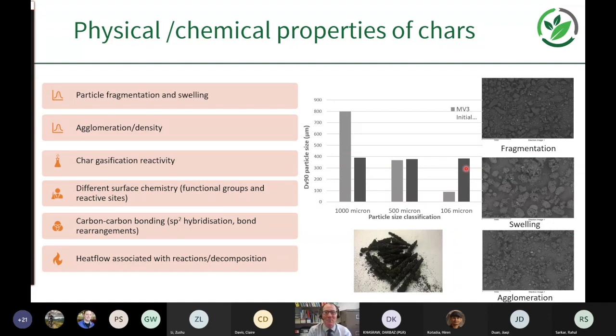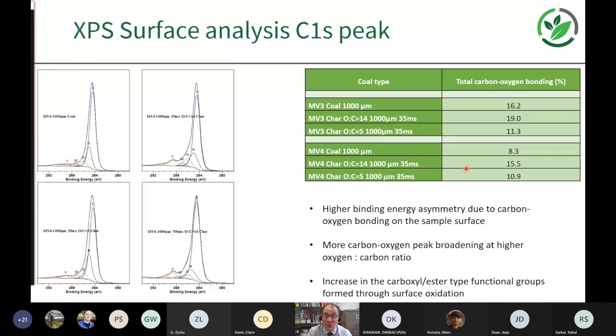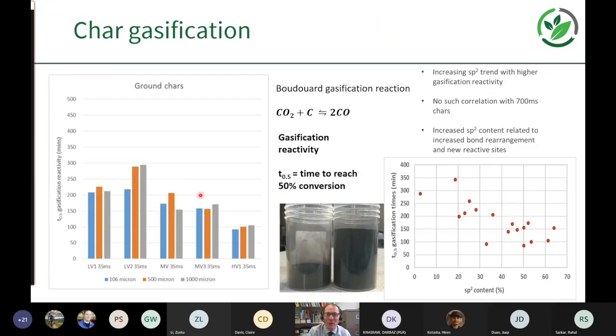it's likely that these chars that are formed then find their way into the blast furnace, and they exhibit different effects like fragmentation, swelling, and agglomeration, all things which are also very applicable to other particulate iron making processes like Finex, for example, or HIsarna. We've used X-ray photoelectron spectroscopy to analyze the surface chemistry and then correlate that with reactivity to try and improve that.